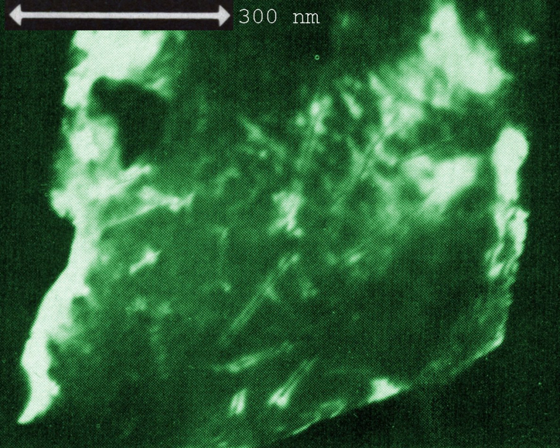The electrical conductivity of the multilayer wire depends on the applied external magnetic field. The magnetic order of the cobalt layers increases with the applied field. Without magnetic field, neighboring magnetic layers prefer the anti-parallel order. With magnetic field, the magnetic layers prefer the orientation parallel with the magnetic field. The parallel orientation corresponds to a reduced electrical resistance. The effect is used in reading heads of magnetic storage media, the GMR effect.